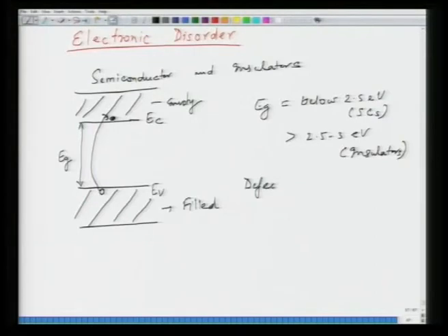In terms of intrinsic point defects, if you look at the statistical model, then in order to create a certain number of defects, you need to overcome the energy barrier of defect formation energy, that is delta HF. Now, here you need to overcome Eg in order to create an electron-hole pair, or to create electronic disorder or electronic defects. So, defect density as a result is nothing but the number of electrons or holes in the material, and you can express it in terms of per centimeter cube.